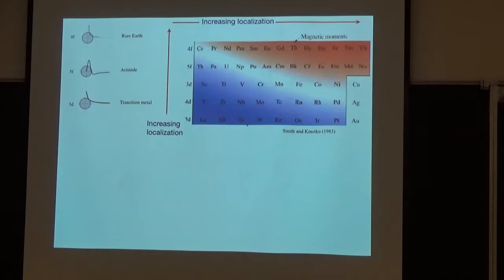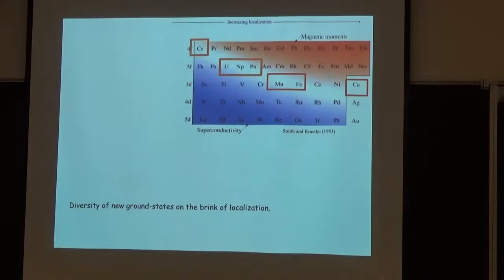Neodymium plays a major role in modern high field iron-based magnets. On the bottom left-hand side, you have superconductors. These are the D electrons in lutetium, hafnium, yttrium, zirconium, all very delocalized. Niobium is a very good superconductor in its elemental form, a phonon-based superconductor. And what we're going to be interested in is the crossover region. And it's in this region that very interesting things happen. And so cerium is not quite magnetic and not quite delocalized. And this is where a whole group of heavy electron materials occur. There are also actinide heavy fermion systems containing uranium, neptunium, and plutonium.